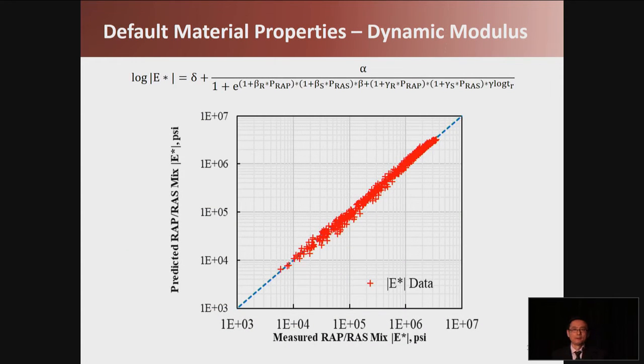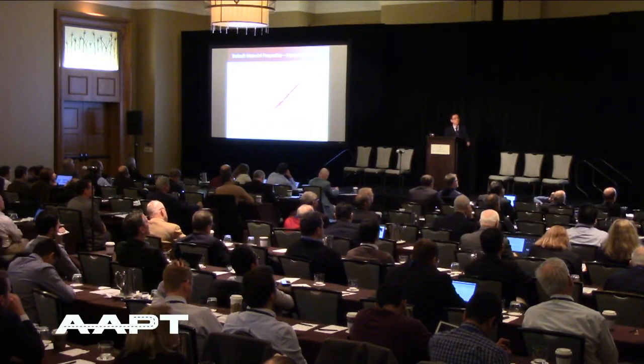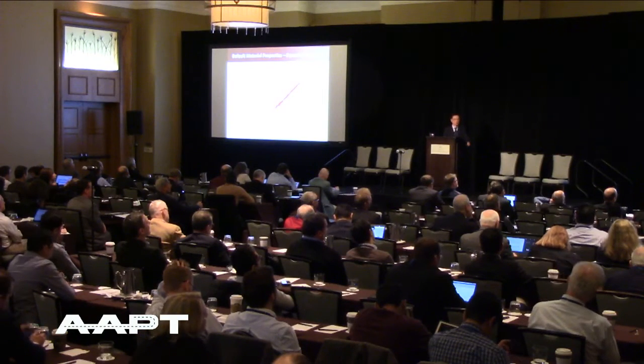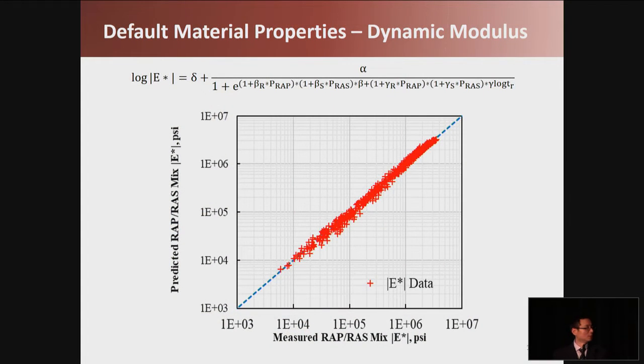So here shows the example for the dynamic modulus. This equation has two parameters: P-RAP, which is the percentage of RAP, and P-RAS, which is the percentage of RAS. That's the RAP-RAS content, and based on that, we can determine the dynamic modulus. In this plot, it shows the equation-predicted modulus compared with the lab-measured modulus. Similarly, we do this test for the fracture properties and the rutting properties. So we develop these default material properties and incorporate these values into the program.